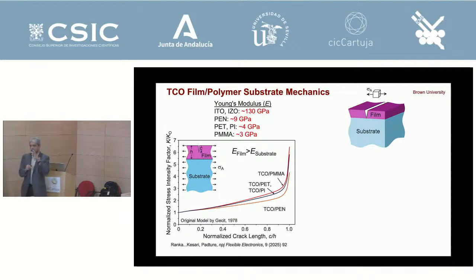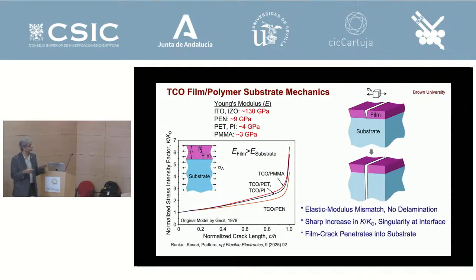The stiffness of the film is higher than the stiffness of the substrate. So at the tip, when it reaches the interface, it creates a singularity with such enormous K that anything would rip apart under that film, regardless of how tough it is. And so that's what we are seeing here. It's primarily due to this elastic mismatch, right?